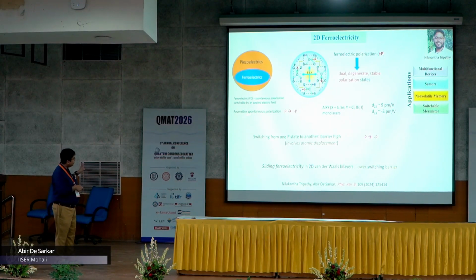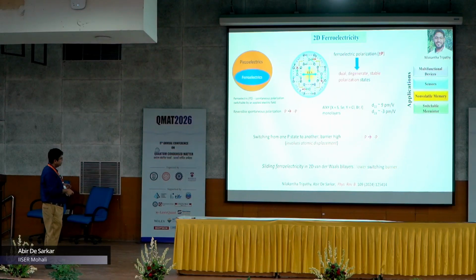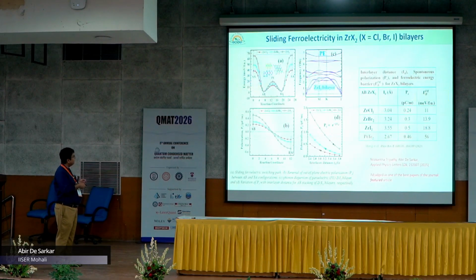Now, how can you get around this problem? How can you circumvent this? If you switch to van der Waals bilayers, where you can slide one layer on top of the other, the barrier is relatively lower. The switching barrier is lower if you move to sliding ferroelectricity, and that was our motivation behind working on sliding ferroelectricity in these bilayers. These bilayers can be exfoliated from their bulk counterparts, which are van der Waals solids.